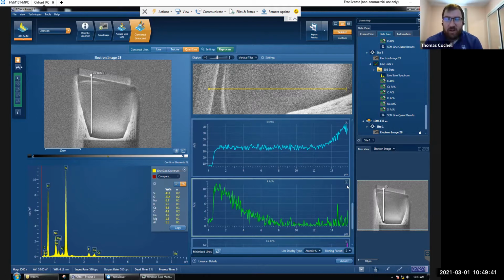I know one of their big questions early on was, we were doing the 100% potassium bath, which is what we're looking at now. We did 100% sodium, which in theory shouldn't do much because sodium's already in the glass, so if it exchanges, it doesn't do anything. And then we did silver, the 5% and different concentrations, on top of either potassium or sodium. They were interested in whether, if you have both silver and potassium, they both exchange, or does one cut out the other? We've done a couple of samples so far, and we're starting to get some data on that. But that might be something we want to look at in the future.